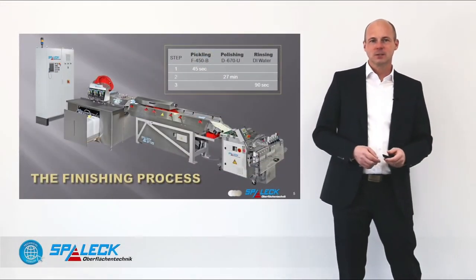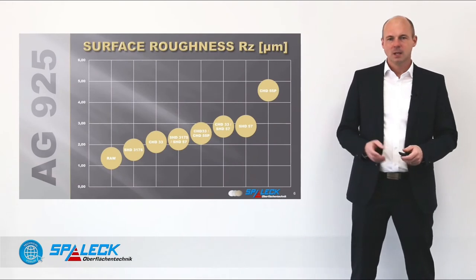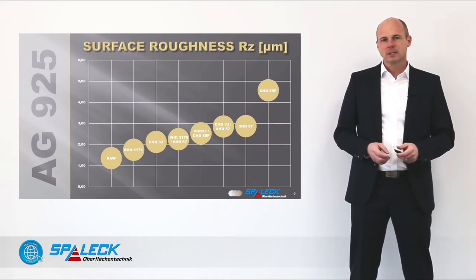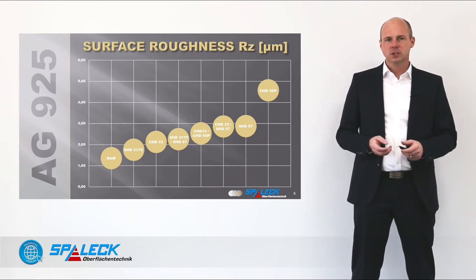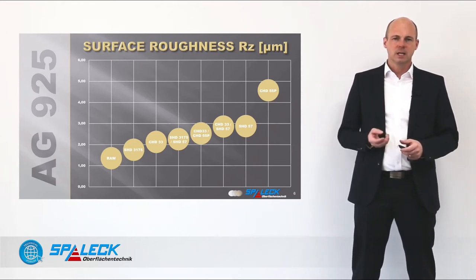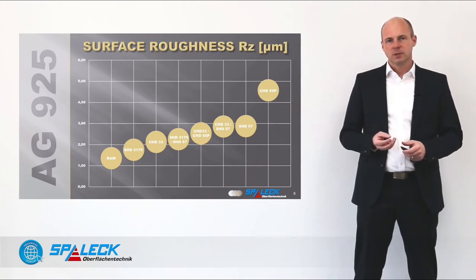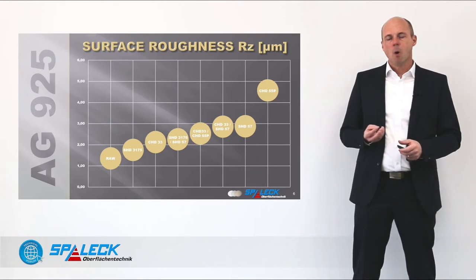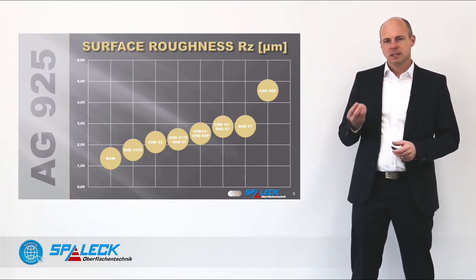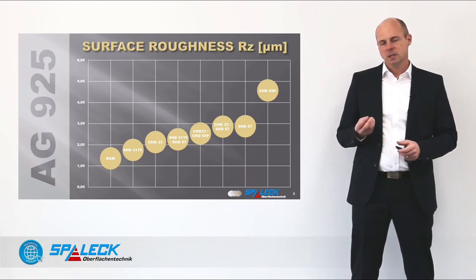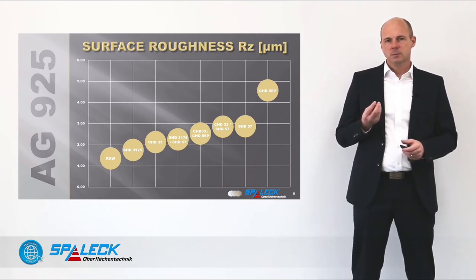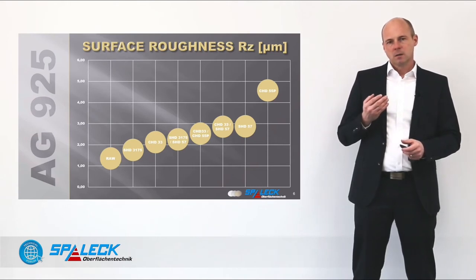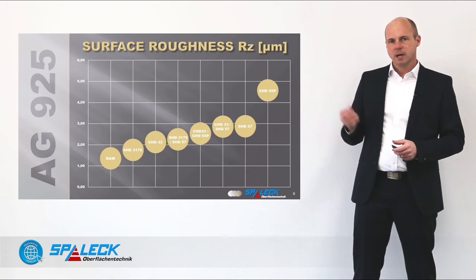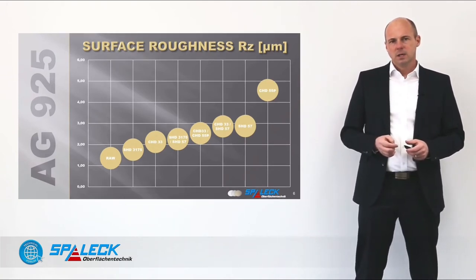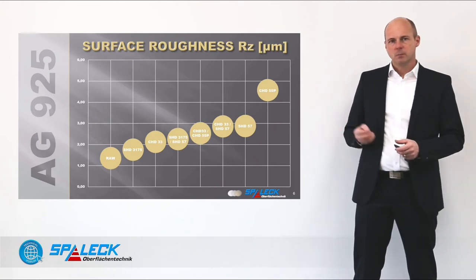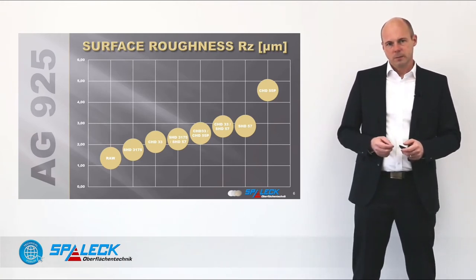So, here are the results of the surface measurement of the sterling silver. You see the different measurements depending on the different media mixtures, which are a result of the weight and also of the geometry of the media. For sure, heavier media like satellites or the pins, in combination with the edges of these media, are generating a more structured surface, which has a higher Rz value than smaller, lighter media like the balls, for example, stainless or ceramic.